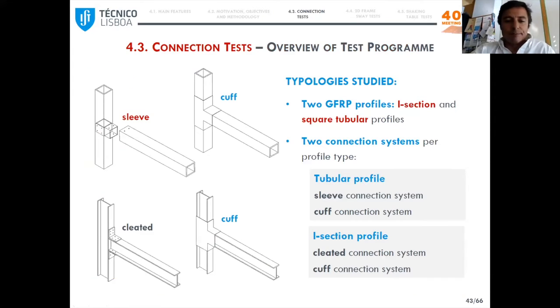So at the connection level, the study focused on 2 different sections of GFRP profiles: square tubular and I section. And for each shape, we developed 2 different systems. So for the tubular shape, we developed first the sleeve system with a stainless steel part that is positioned inside the GFRP beam and column. So these parts are not visible. And a cuff connection system comprising an external stainless steel part, which is much easier to install. For the I section profile, we studied the same cuff system and an additional one involving stainless steel cleats as an alternative to FRP cleats.